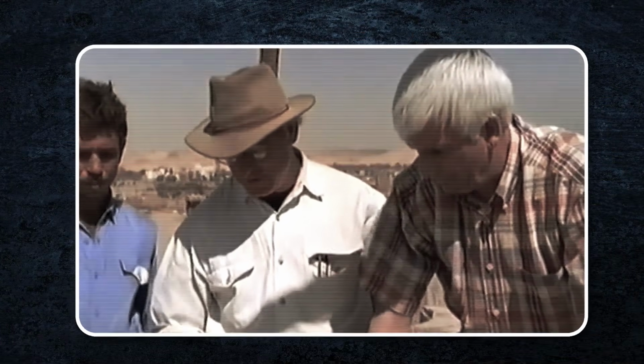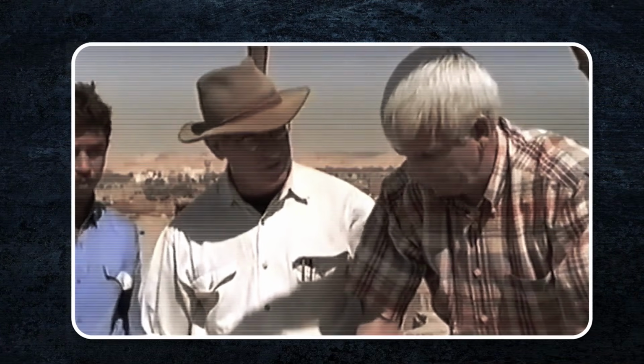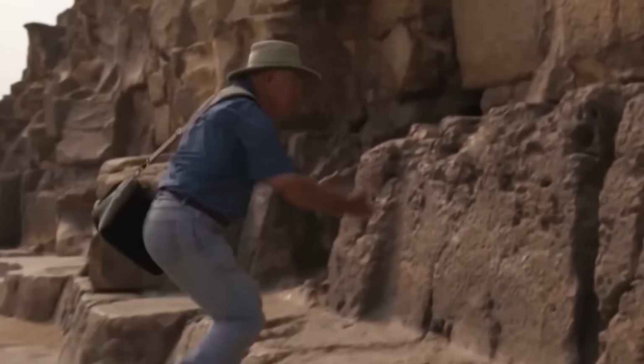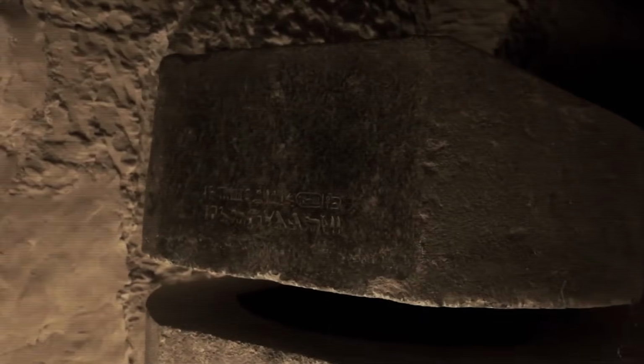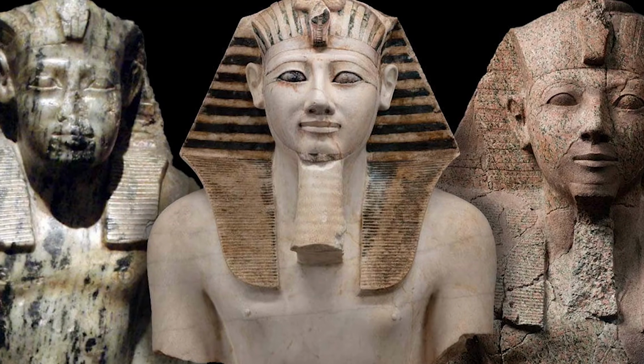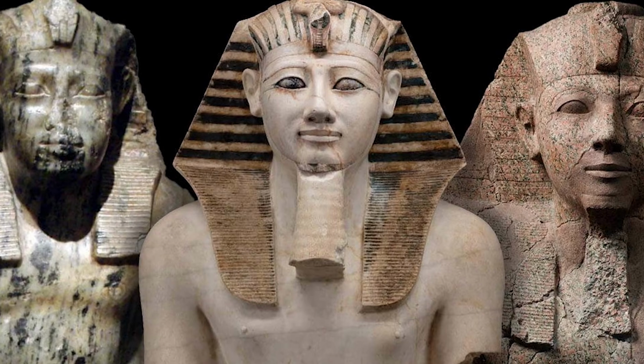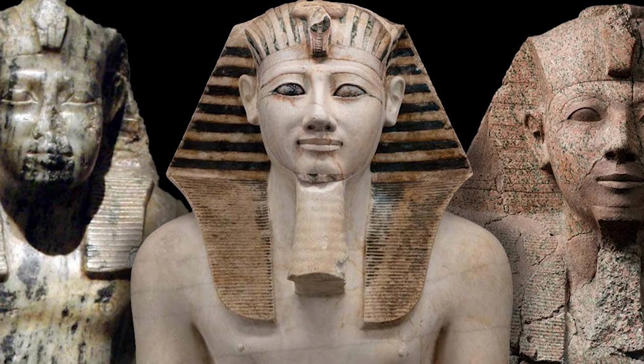Second, copper tools with ground quartz powder, slightly finer and more consistent than sand, but chemically identical, marginally better, still measured in fractions of a millimeter per hour, still rough. Third, copper tools with a slurry containing corundum mixed with quartz as a carrier medium. The change was immediate and striking. The copper stopped fighting the granite and began directing the abrasive efficiently across the cutting surface. Resistance dropped. The cut became smooth.